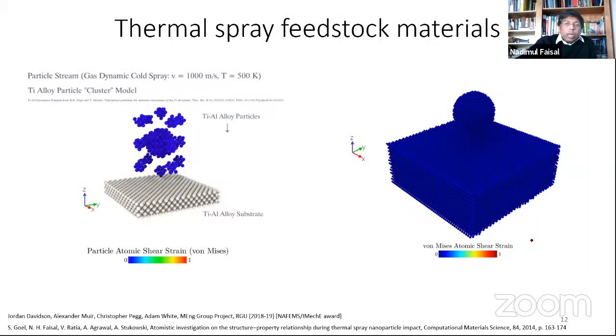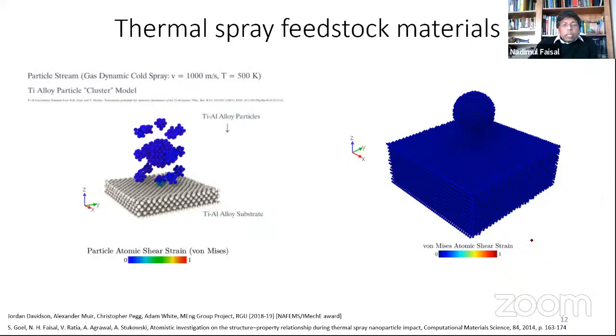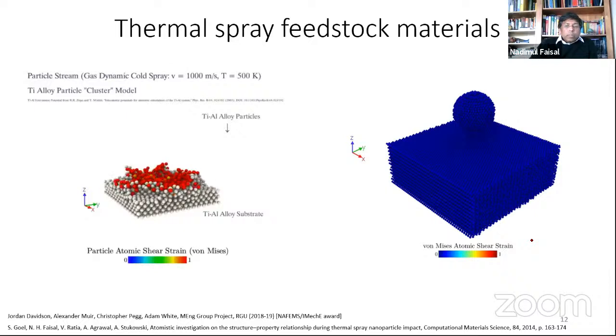Right, so to understand what happens theoretically, we did some work using the molecular dynamics simulation technique. The first work we did with Dr. Saurabh investigated a copper powder particle on a copper substrate. And a couple of years ago, we did a project with our final year project students, where they simulated multiple particles sprayed onto a substrate. You can see as it is sprayed, the strain builds up. Based on the size of the particle, you can see some features in it.